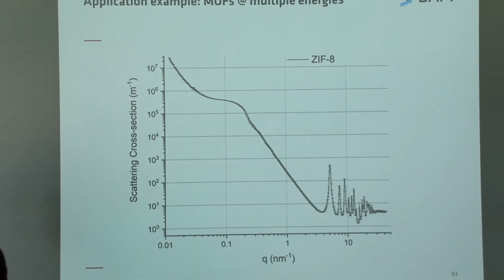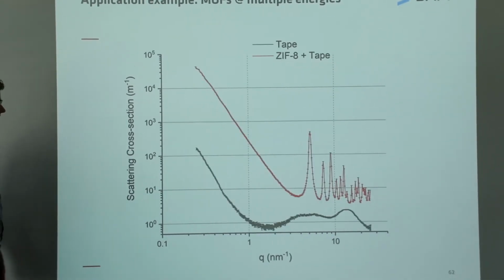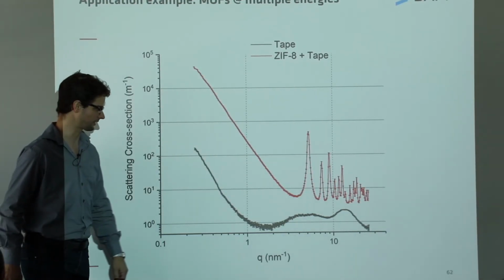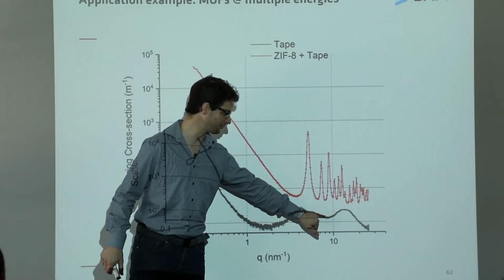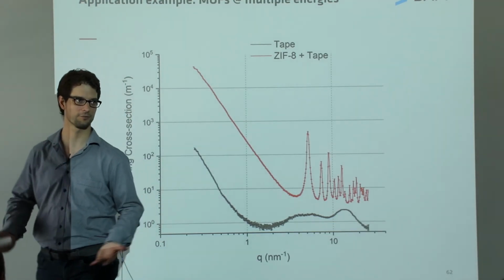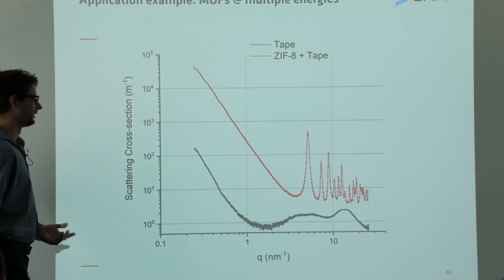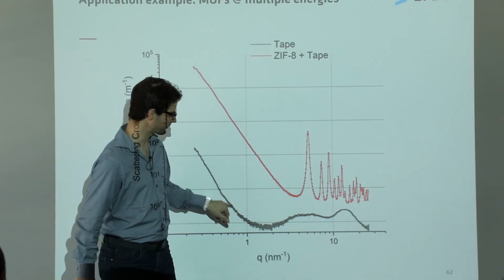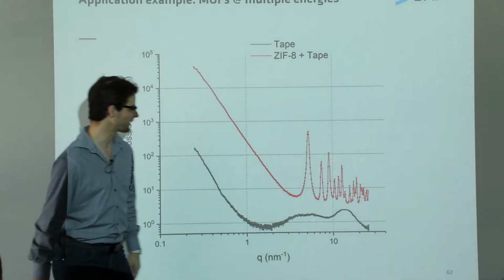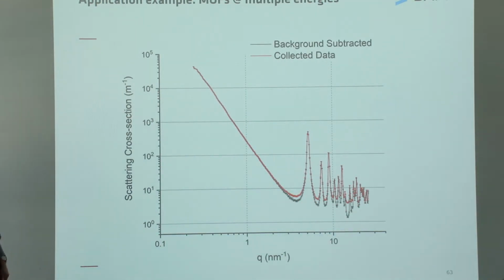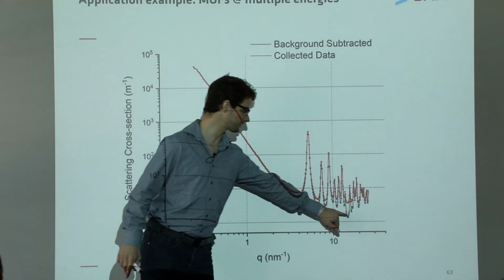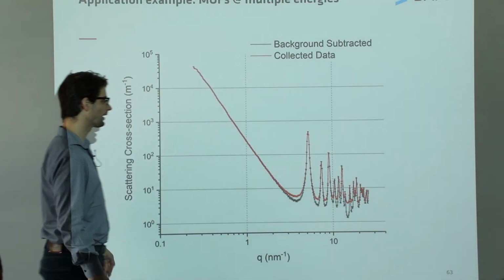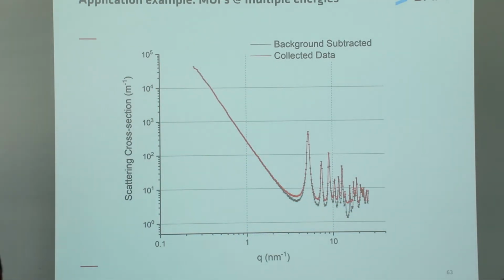The complete data set looks like this. We have corrected it, of course. In this case, we subtracted the tape background. We use the same Scotch magic tape that everybody uses. Sandwiching our powders in between, and this is the signal from that. So the correction isn't big, but your peak profiles actually become a lot better, especially at the lower intensities.